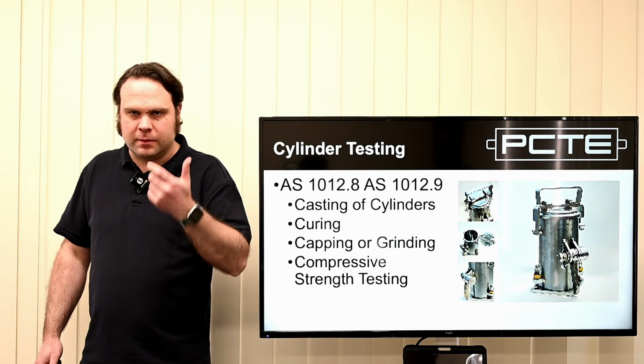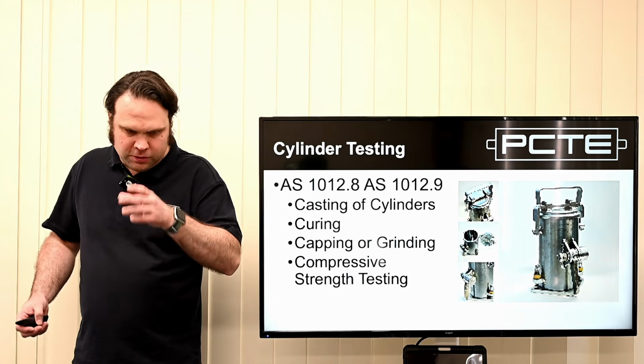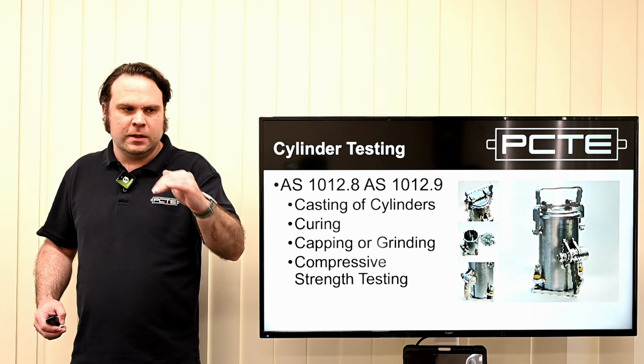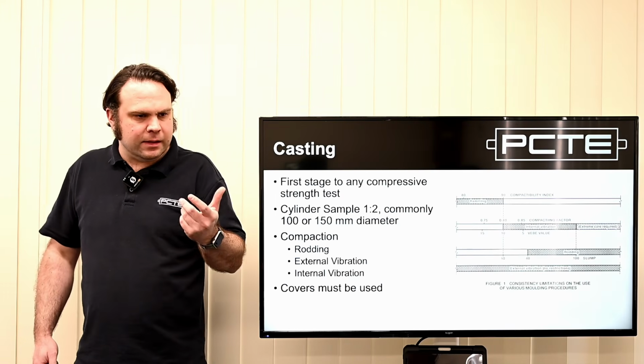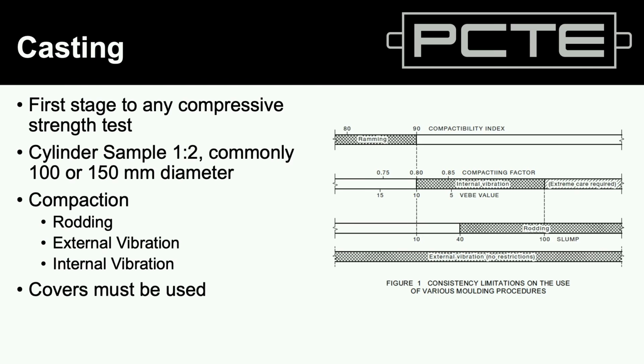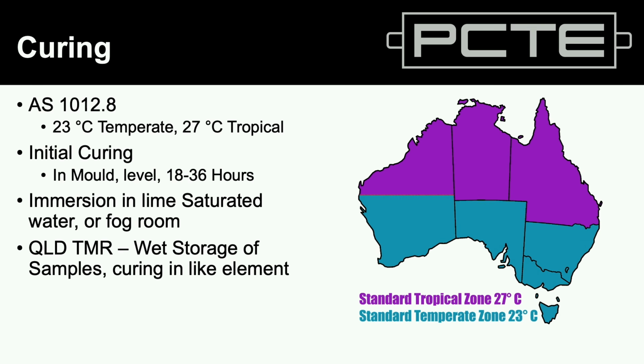So I've got a standard cylinder mold here, 2-to-1 ratio, 100 by 200 millimeters high, cylindrical, cast in stages, with the sample compacted using either rodding, external or internal vibration, and covered and protected from the environment. Leave a cylinder out in the sun, it's not going to break the same way as if it's protected. And the curing situation is we need to get the solidified cylinder sample out of that mold between 18 and 36 hours, and we'll do so into a saturated lime water bath or a fog room at 23 degrees in the lower half of the country, or 27 degrees in the tropical regions in the top half of the country up in Queensland and similar.